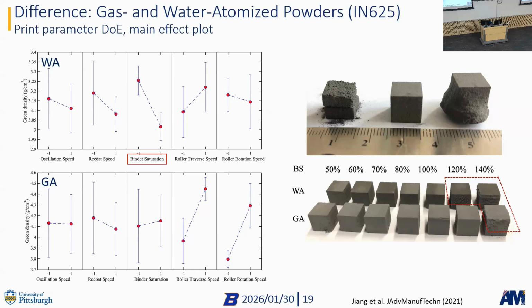What we saw is that for these two different powders, water atomized and gas atomized, the main effects of the print parameters, so basically what affects the green density the most, are actually very different. For water atomized powder, it was just binder saturation. That had a big effect, the other ones really not much. For gas atomized powder, it was the roller traverse speed, so how fast you're spreading your powder, and then how fast you're compressing your powder with the roller. Right? So that was very interesting. So we optimized this to the highest density, and then we just modified binder saturation for both.